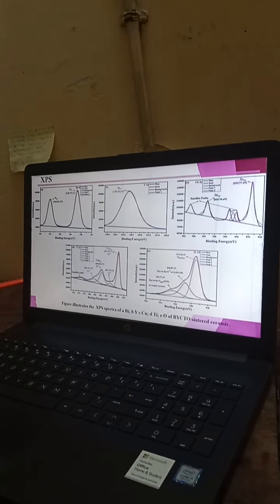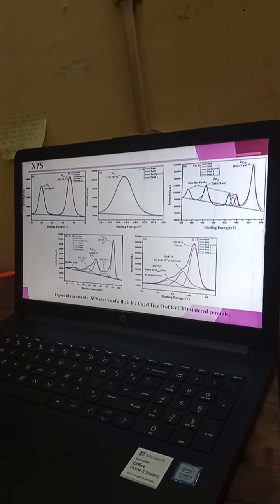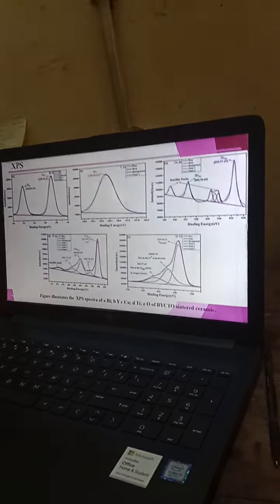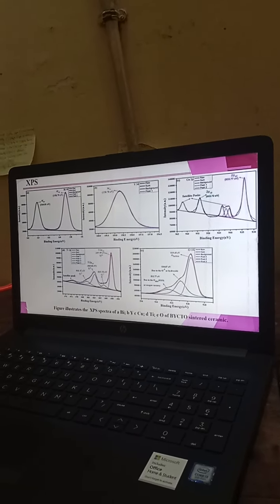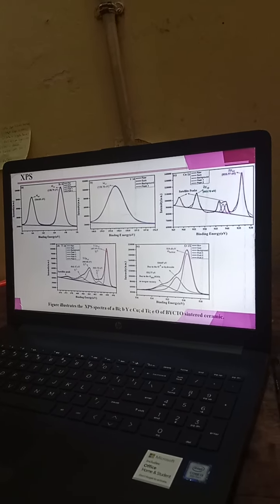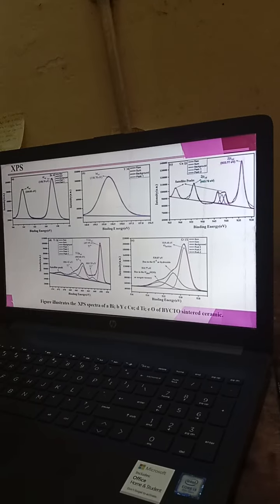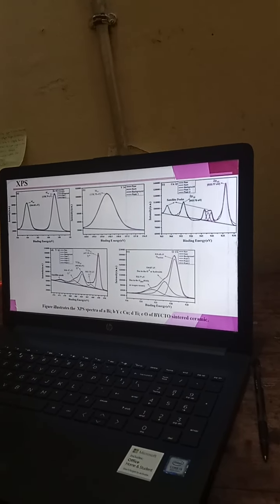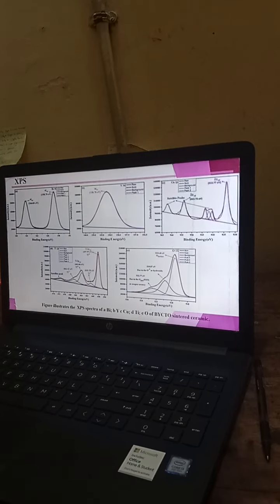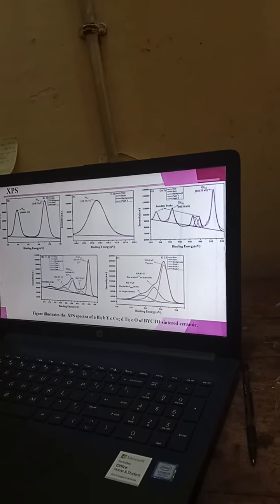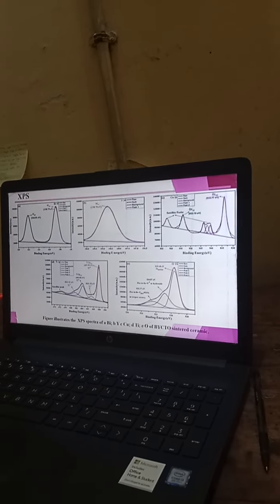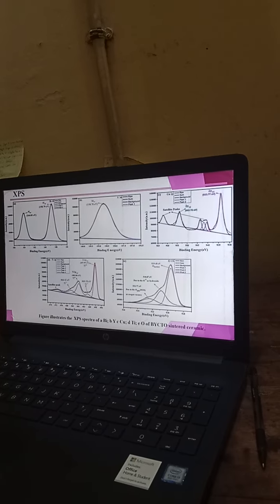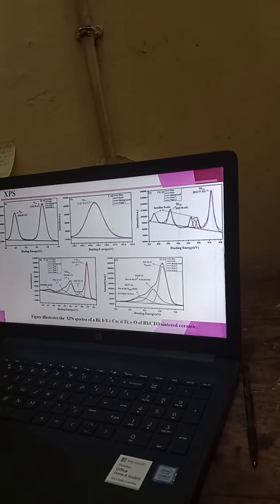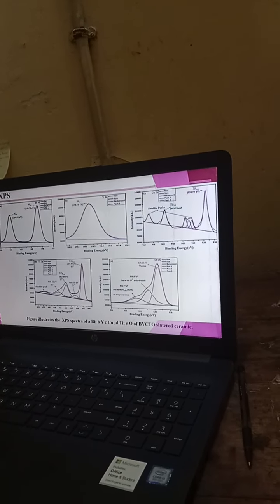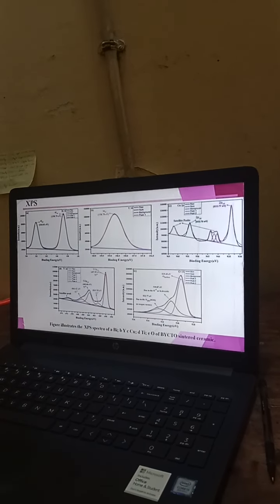Figure E represents the oxygen 1s XPS spectrum. In this spectrum, we have observed three peaks. One is around 529.48 electron volt that represents the metal oxygen bond in the crystal lattice, the peak around 530.87 electron volt is due to the adsorbed oxygen or hydroxyl group, and the peak around 532.77 electron volt is due to the oxygen vacancy.